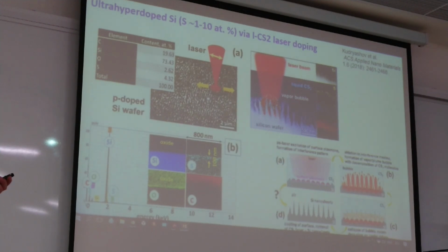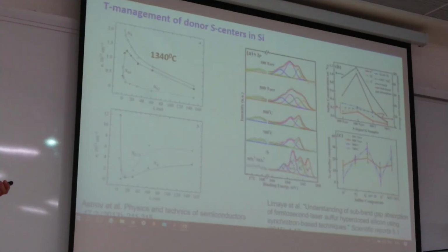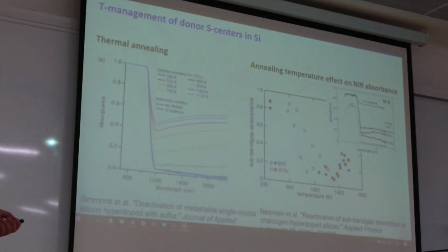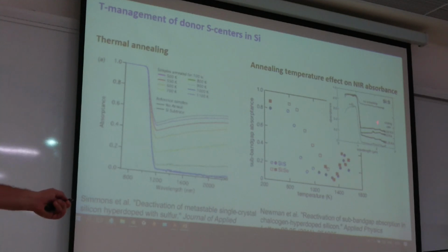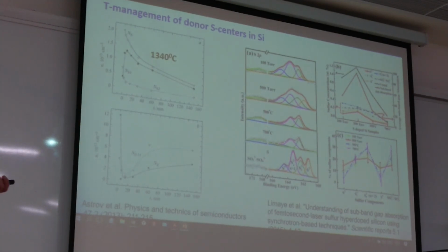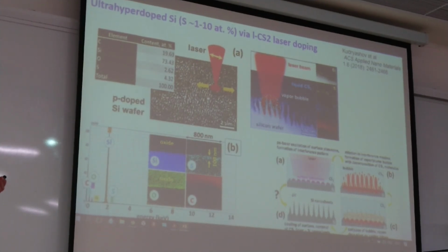And occasionally in our work, limited by our oven which we use for annealing, we have chosen this minimum of sulfur concentration and minimum of near-infrared absorbance. But we have got just the opposite and very extraordinary results in our case. So thermal annealing was done at 1200 degrees, and as a result of annealing we produced an almost flat silicon surface. So these kinds of spikes were oxidized and just delaminated from the surface. So the sulfur was in the top layer of silicon.